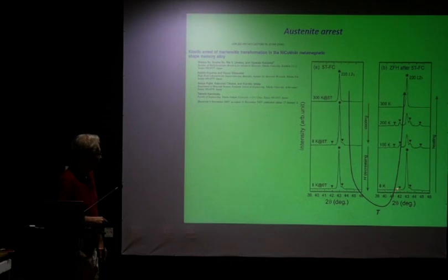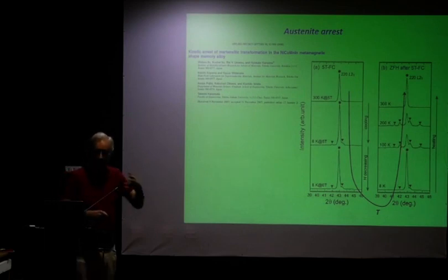increase the temperature. And what happens is that when they come to about 100 Kelvin in zero field, this is zero field warming after the 5 Tesla cooling, so you remove the field here, this is all zero field, you see that this martensite state starts reappearing again.